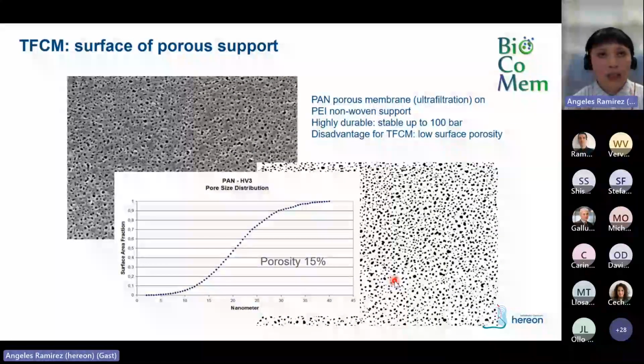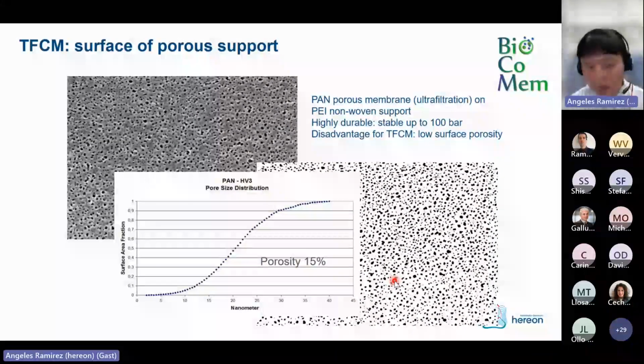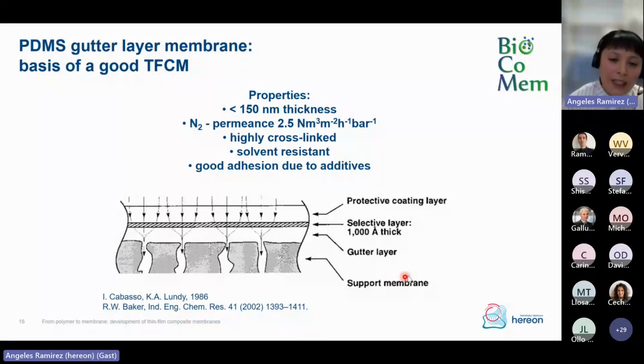So in order to improve the gas separation performance of the membrane, we can proceed to coat or to activate the support by the deposition of the so-called gutter layer. This very thin layer we coat by using, for example, polydimethylsiloxane, which is a very fast polymer with a very low selectivity, but fast and very robust, that is solvent resistant and has adhesive properties. So this gutter layer will act as a very smooth and adhesive surface that will facilitate the addition of the selective layer on top. And most importantly, it will work as a drainage layer of the gas, as you can see here, from the selective layer to the next available pore. So this will make the membrane faster.